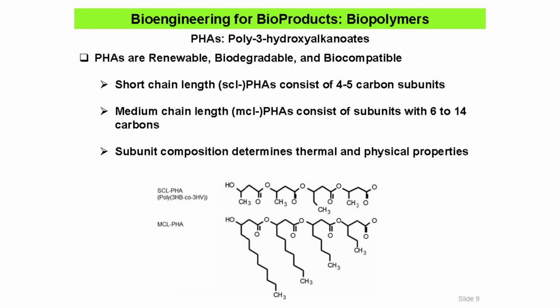The advantage of PHAs, the polyhydroxyalkanoates, is that they're renewable, they're biodegradable, and they're biocompatible. So anybody ever had oral surgery? I've had oral surgery, right? So they put sutures in your mouth, and then eventually they disappear. Well, those sutures are made from polyhydroxyalkanoates, from very short chain PHAs, because these PHAs can either be made of short chain length subunits that have 4 or 5 carbons in them, or medium chain length PHAs which have 6 to 14 carbon subunits in it. And you get these kind of chains, either a short chain one or a medium chain long one with different chain length side chains.